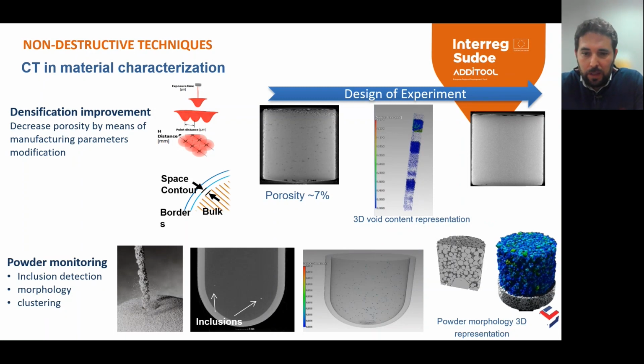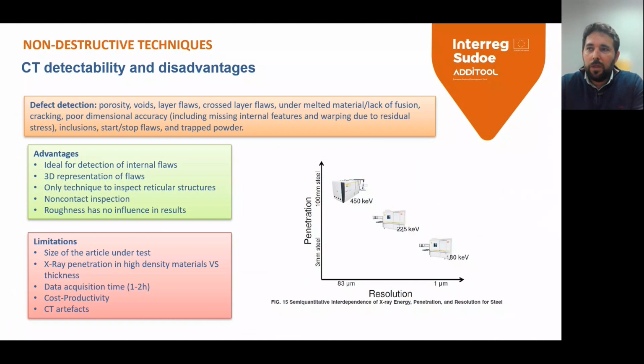Another usage of CT is to inspect PBF raw material, metallic powder, looking for inclusions, as I showed you before. These are 2 inclusions, or even high resolution inspection to analyze powder. As you can see in here, we perform this type of inspection for seeking the morphology and clustering, and also to analyze the powder degradation during the usage of the powder. So this technique is also capable of detecting almost all the AM defects, and what is more, showing 3D information about the location and shape of the defect. That is why it's a powerful tool during process development.